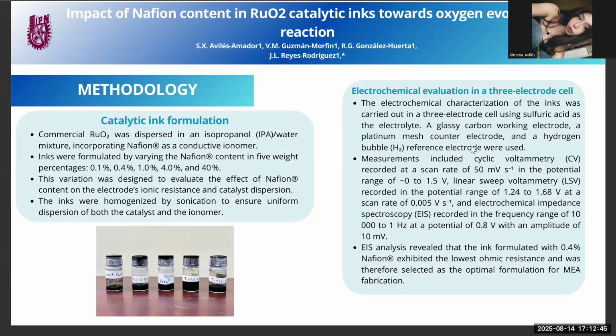We used commercial ruthenium oxide dispersed in an isopropanol-water mixture with NAFION added in different weight percentages: 0.1%, 0.4%, 1%, 4%, and 40%. The inks were homogenized by sonication to ensure uniform dispersion. We tested each ink in sulfuric acid electrolyte using a glassy carbon working electrode, a platinum mesh counter electrode, and a hydrogen bubble reference electrode.